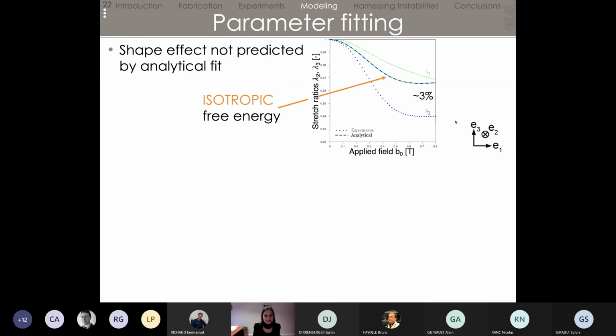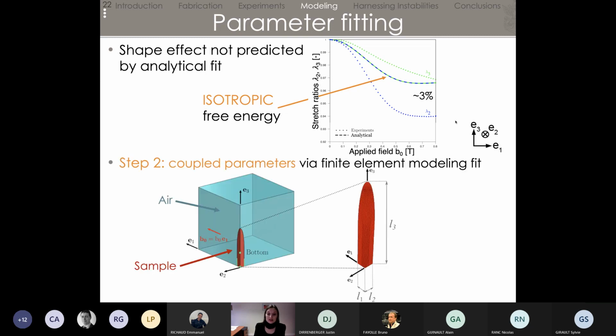Now, what's more problematic is when you identify those parameters and look at the response of your model for the transverse stretch ratios: you see that the model predicts the exact same response for the 2 directions that technically are the same in an isotropic sample, even though they are not the same when we measure them on our ellipsoidal sample. And we cannot do much about it because the model is isotropic, so it will always predict something identical in those 2 directions. So the only way, if you want to identify the parameters, is in the end to conduct this identification via finite element modeling. So you have to mesh your whole sample.